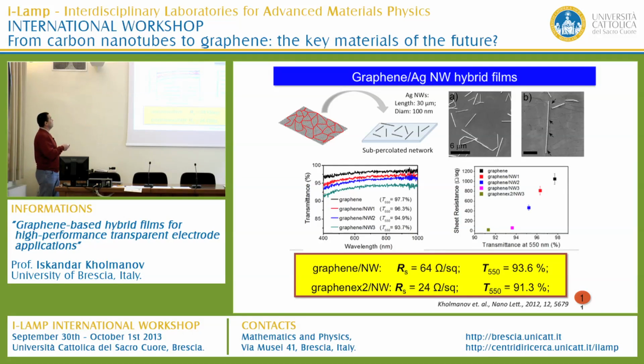So following this idea, we experimentally obtained graphene silver nanowire hybrid films. In this case, our silver nanowire films are not globally percolated. So they have no global electrical conductivity, but they can increase the electrical conductivity of graphene just locally. So what we did, we transferred CVD grown graphene on top of the silver nanowires, and this is the AFM image of the hybrid film. If you see here, there is one single nanowire crossing several line defects, and in this configuration, it connects this graphene domain with this one, so eliminating the effect of these line defects in the electrical conductivity properties.